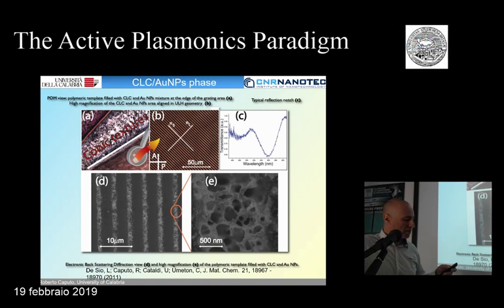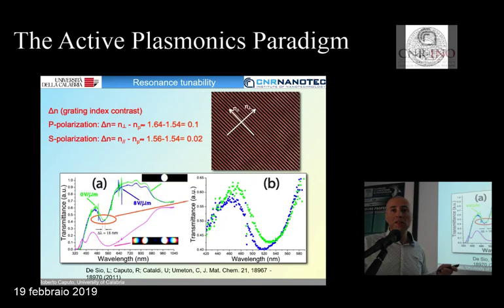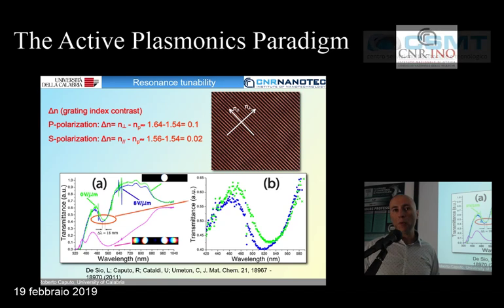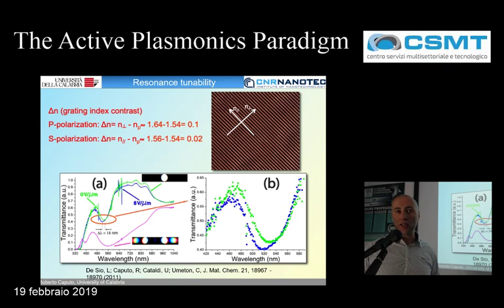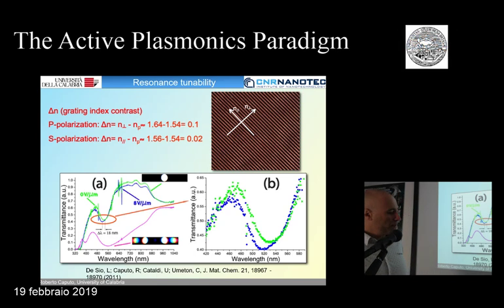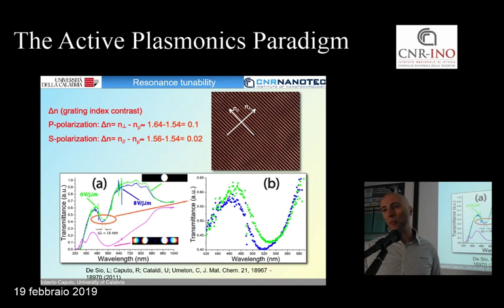And this is what a polymeric grating becomes when you infiltrate it with this kind of liquid crystal doped with nanoparticles. This is an SEM backscattered image, which confirms the massive presence of metal nanoparticles. And this system has some remarkable plasmonic properties, because indeed, when you apply an electric field to the system, you modify the orientation of the liquid crystal, and in some way, you have a first example of active plasmonics, because the liquid crystal, in this case, is the surrounding medium of the particles, and what you get is this kind of shift, which is not very remarkable. It's about 18 nanometers, but the nice point is that it is controllable externally by an electric field.